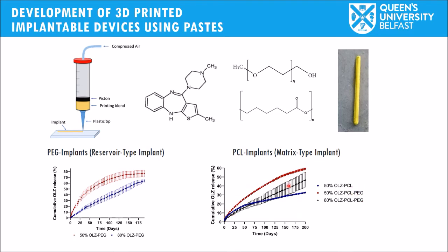In order to get a more sustained drug release, by increasing the percentage of drug in the implants containing polyethylene glycol and polycaprolactone, we get a linear release profile. So that shows that this technology can be used to tweak the release from the implants in a really easy way, in a really simple way, by using different paste formulations. Obviously the devices need to be dry before they can be used.